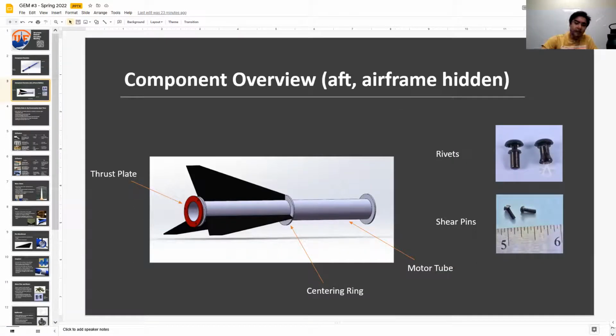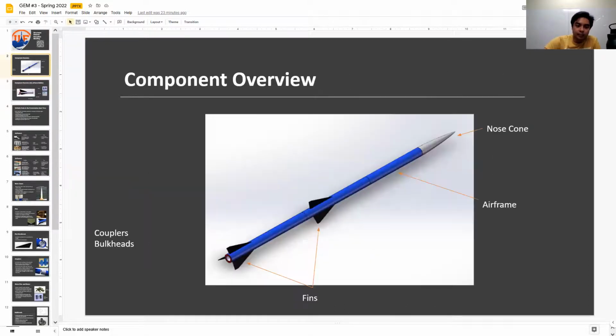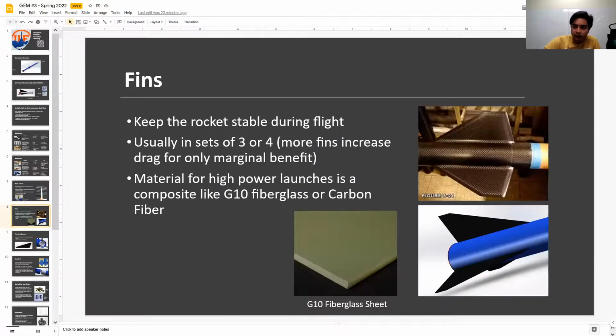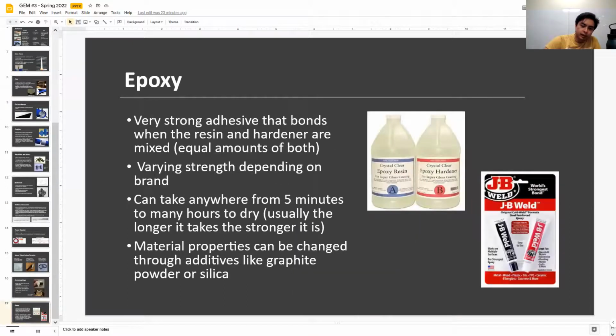Crystal Clear epoxy is a very nice epoxy. When it cures, it's glass-like and very smooth. So it's very desirable to have rock epoxy on the exterior of the rocket. If you see here on the carbon fiber, it makes a very nice fillet on the exterior of your rocket. If you use JB Weld, it'll be a little bit more clumpy and it won't spread as nicely. Some other stuff we use is 5-minute epoxy, but we mainly use 5-minute so that it holds it in place until we can use either JB Weld or rock epoxy. So we would use 5-minute epoxy when we're doing fins so that the fins don't shift while the really nice epoxy is curing.